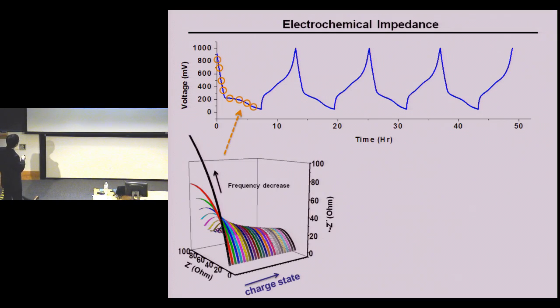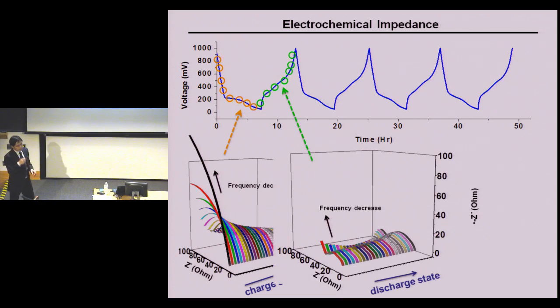You can see here, as we charge it, the semicircle actually decreases. That means as we put more lithium into the silicon, it becomes more lithium-ion conductive. So this is the reason why we have this decrease of the semicircle. And as we take away the lithium ion from the structure, the semicircle starts to increase. So these two measurements are consistent.